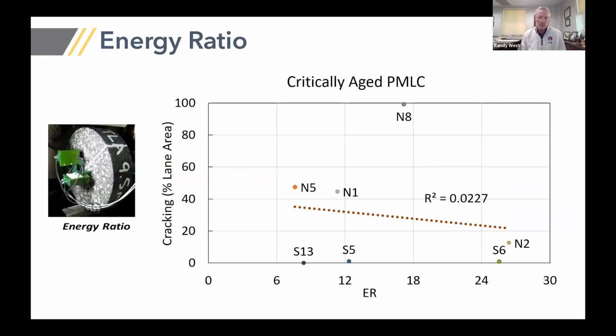Another way to look at the data is just with an XY plot, and on the X-axis is the energy ratio, and the Y-axis is the percentage of lane area cracking. And we would expect, if the test is a good correlation to field performance, that this regression equation shown by the dotted line would fit well, and it'd be a nice linear relationship or a relationship that fit well to the data. R squared is our coefficient of determination, and when that's 1, it means it's a perfect correlation. When it's close to 0, it means it's not so good. In fact, this one's showing it's very, very poor, close to 0. So I'm going to show those 2 charts for all these other tests.